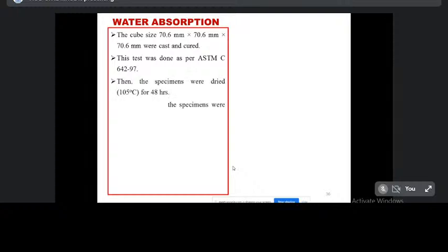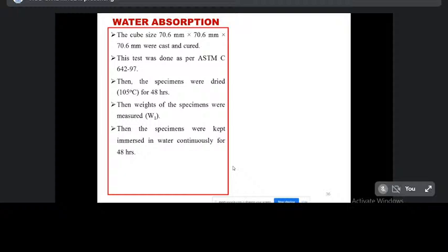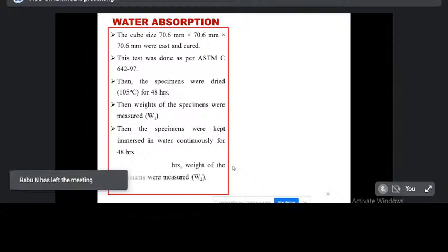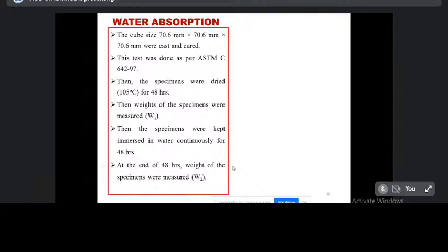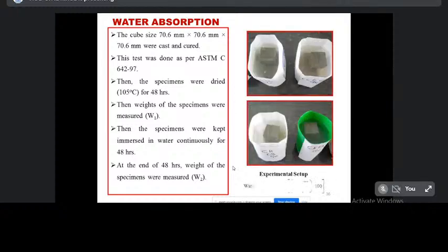Next, we move to water absorption. For water absorption, I have prepared a cement mortar cube of size 70.6 mm by 70.6 mm by 70.6 mm. This test was done as per ASTM C642. Then the specimens were dried at 105 degrees centigrade for 48 hours. Then the initial weight is measured. That initial weight is denoted by W1. Then the specimen was kept immersed in water continuously for 48 hours. After the 48 hours, again we measure the final weight. That is denoted by W2. Then this is the equation to find the water absorption percentage: W2, final weight minus initial weight, divided by initial weight, times 100, gives water absorption of the given specimen.